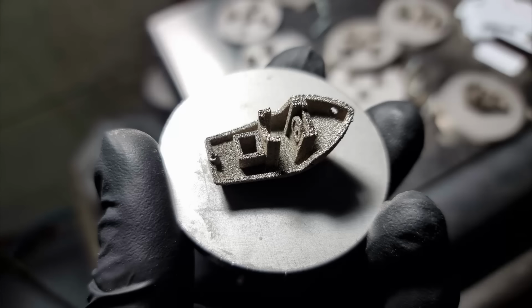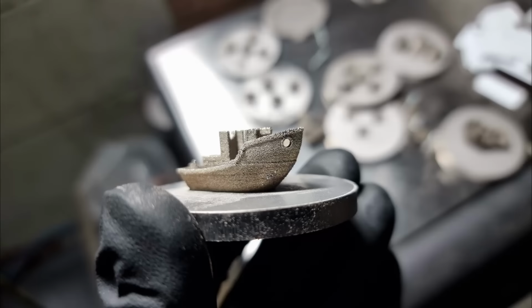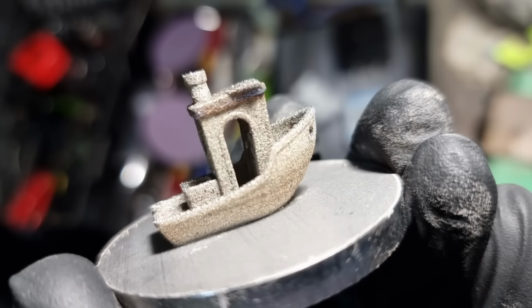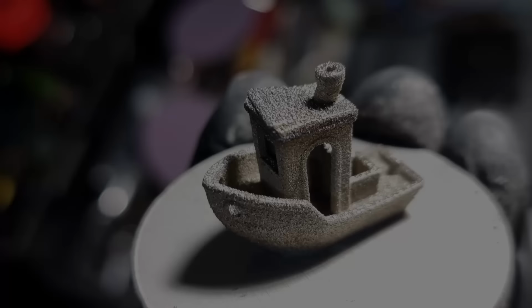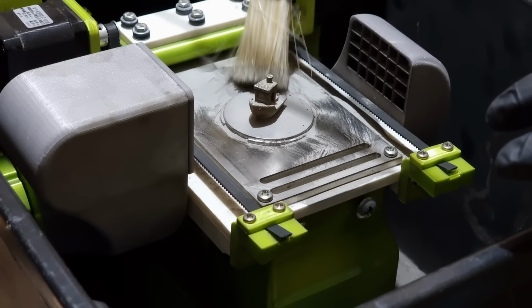The second benchy would fail due to me underestimating how much powder was in the hopper, and the third would fail with me realising the step size was also responsible for the shortage of powder. The fourth benchy would fail at the 11th hour due to the build piston breaking free, and finally, the fifth benchy would allow me to call it done.